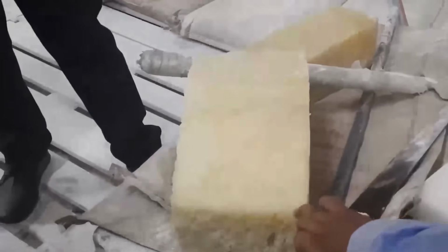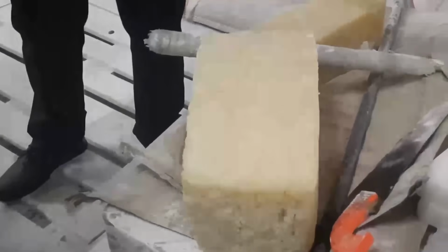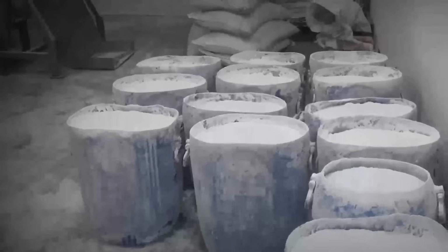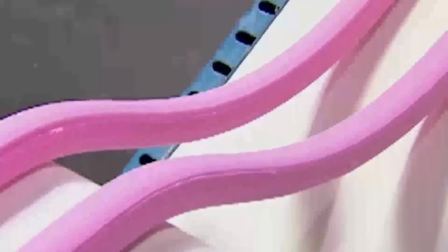The various pre-measured ingredients are added to the mixer in a specific sequence. First, the elastomers are introduced and given time to soften and break down under shear force. As they begin to form a uniform mass, resins are added to bind the structure. Waxes and plasticizers follow, blending smoothly into the mixture to help reduce internal friction and improve processability. This mixing process is not quick.